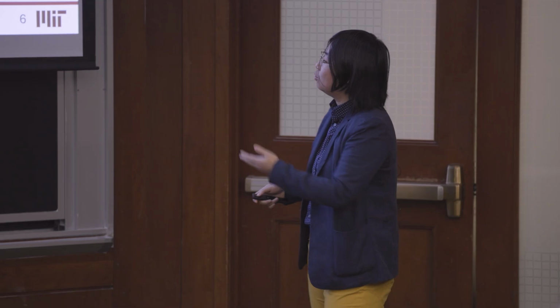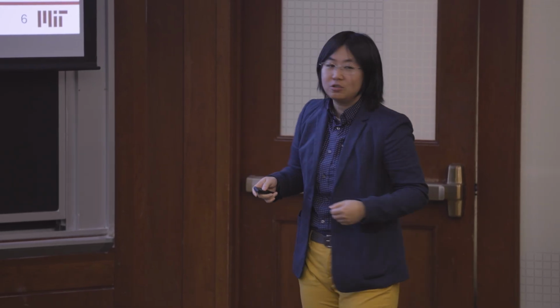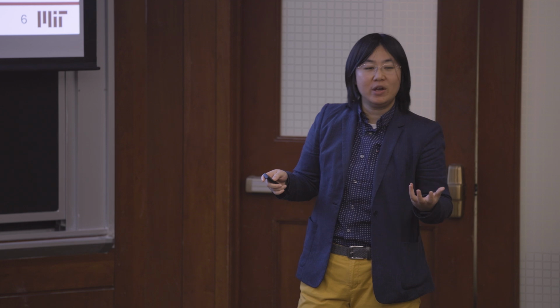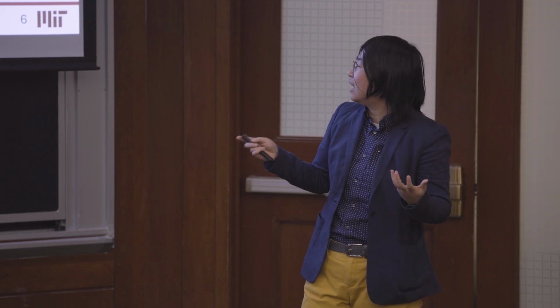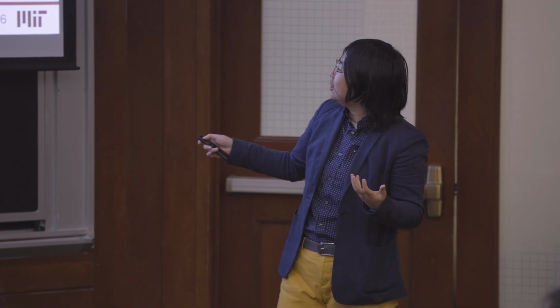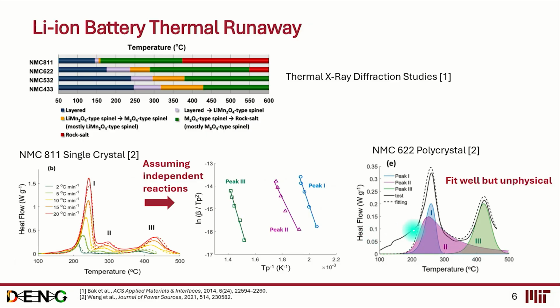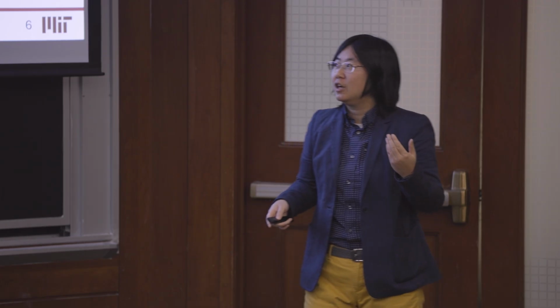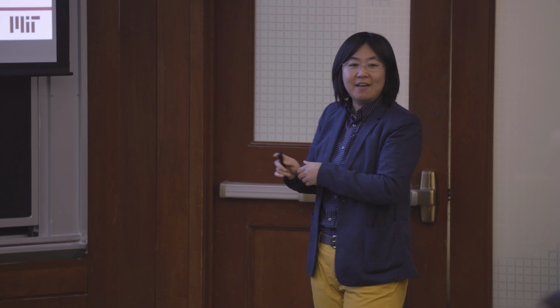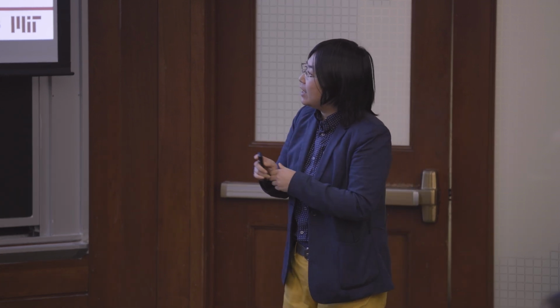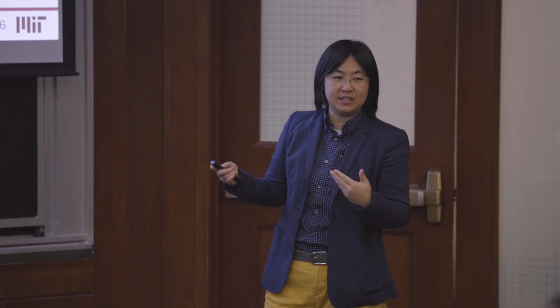Therefore, the naive way is to try to fit 3 peaks to the 2-peak measurement. Well, you can always do that because it's just data fitting. However, it's unphysical. You can take a look at this purple-colored shaded area. Basically, what this means is that the second-stage decomposition starts to happen even before the first stage happens. So this tells us one very important lesson. For any data-driven modeling approach, you could fit the model to the data very well. However, you could be unphysical, right, which would prohibit you from having a reasonable and predictive model.